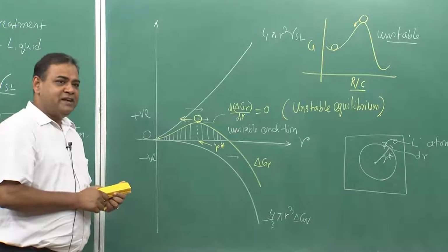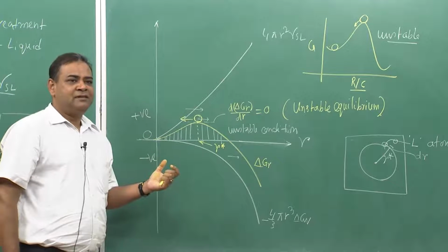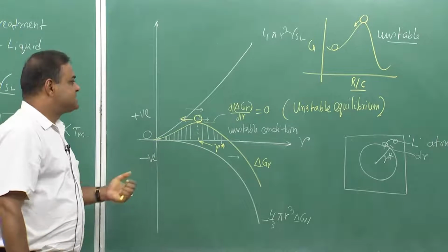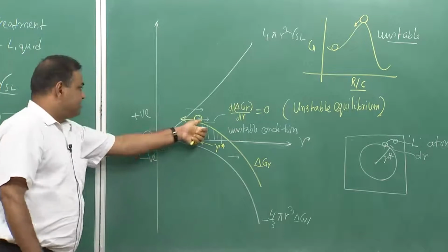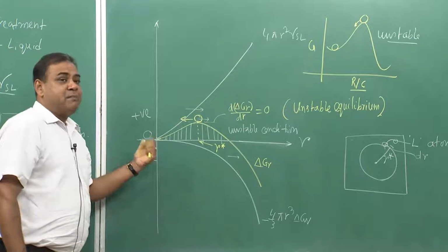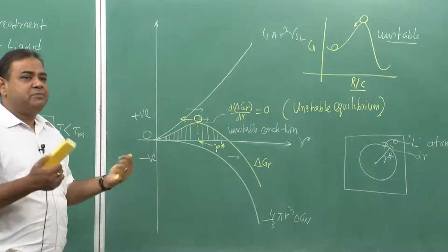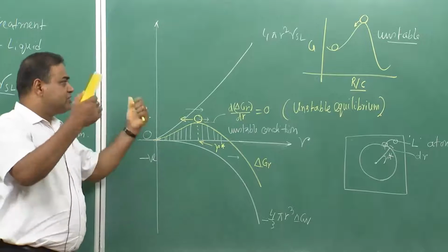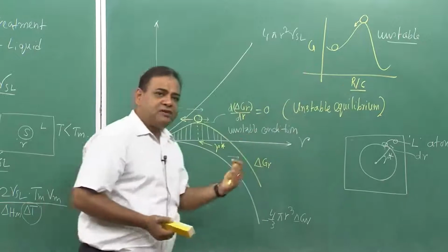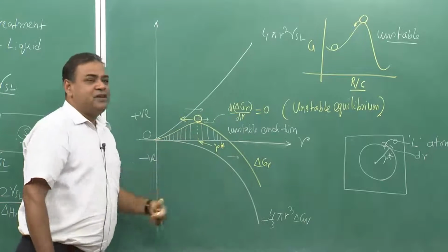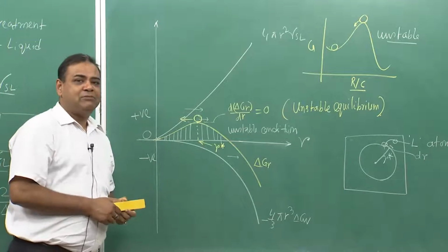So, that means it can only increase its size. What does it mean? It means that the solid becomes a stable particle inside the liquid. The solid cannot go back and melt. So, from this to this way it melts again, and this to this way it actually takes more liquid atoms and becomes solid, solid and solid. So, the solid grows in size. So, this instability as per this model is always good, because that time the solid can go and increase its size. So, that time we call it a stable nucleus.